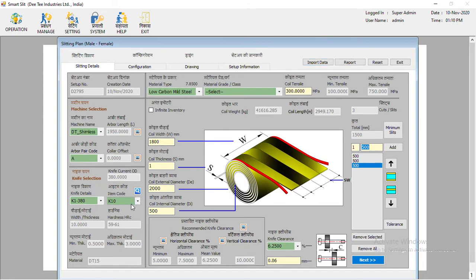So what I was telling you, if I select 1 mm low carbon steel, this is the application: minimum thickness 0.5 I can slit, and 3 mm maximum. Before I select, it does not show anything here. When I select low carbon, it shows 0.5 to 3 mm. When I select medium carbon, it shows 0.5 to 2. Simultaneously it is also showing tensile strength on the right hand side, where you input the coil tensile strength. So that is also varying. Like for stainless steel, I can slit 0.5 to 1.5 and tensile strength 200 to 500.